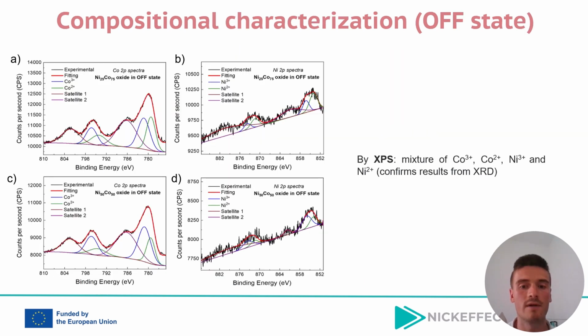The chemical environment of the cobalt nickel oxide microdiscs in the off state was studied through X-ray photoelectron spectroscopy analysis. The cobalt 2p and nickel 2p spectra for two different compositions studied, basically the most cobalt rich and the 50-50, are shown. The fitted spectra indicate the presence of...